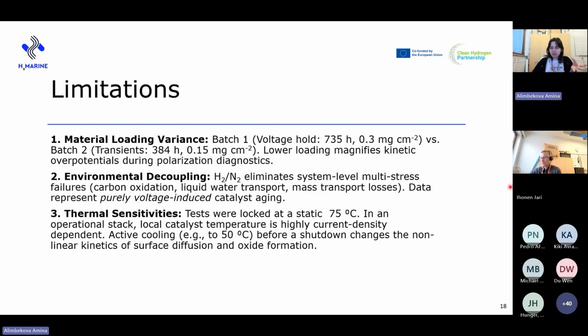We must also address the thermal dependencies, because when used under hydrogen-nitrogen, the thermal profile of the stack is quite even compared to when the fuel cell stack is running under load. We have isolated the voltage and frequency effects under a static 75 degrees.